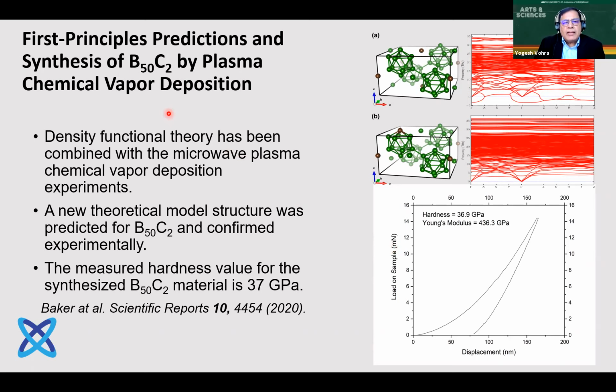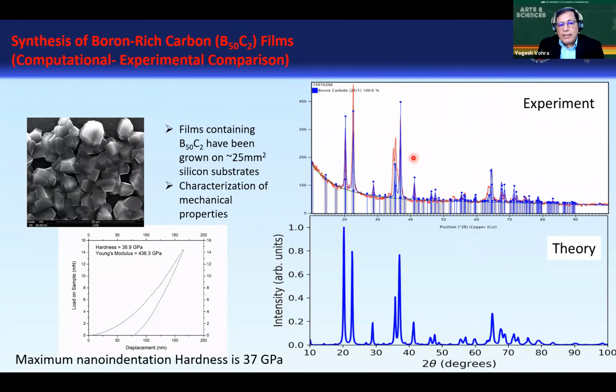Again, theory has predicted a material B50C2, which is predicted to have also high hardness. And there was a crystal structure proposal from theory, so this was what was proposed in the literature. And what we found out is when you do the phonon calculation, you found that some of the modes have negative frequency, meaning that this structure is unstable against displacement. And so the theory predicted a stable structure. And this high boron content material was synthesized for the first time by plasma methods.